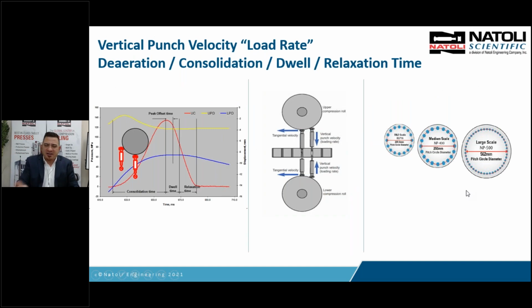All right, one last thing I want to talk about when talking about scale up and looking at presses from one size to another is the punch vertical velocity. This is the consolidation time. This is also called the vertical velocity or the loading rate. This is a function of the compression roll diameter. So if you had a real small roller, that punch is going to hit that roll and come down real fast. If you had a real large roller, that punch hits the roll, it's going to come down at a slower velocity. It's going to have more consolidation time to get that air out.